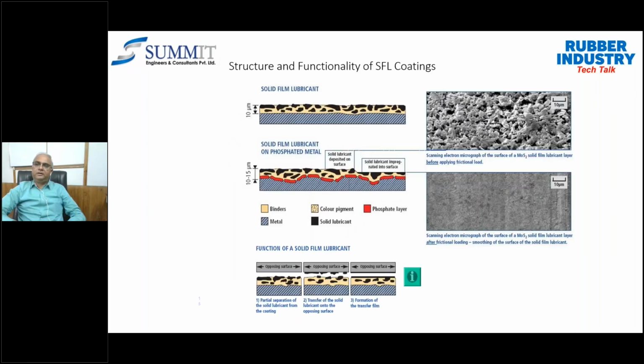Unlike any other coating preparation or coating application, the preparation of the surface is also equally important. Okay, and if the surface is not properly prepared, then the solid film lubrication will not be applied in a uniform manner. Just to explain that, I have given one example of a solid film lubricant on a phosphated metal, and how it could be behaving or applying as a dry film lubrication. In the first figure you'll be able to see that a substrate has been coated with 10 microns of solid film lubricants. Now, the metal has been coated with the phosphated pre-treatment,